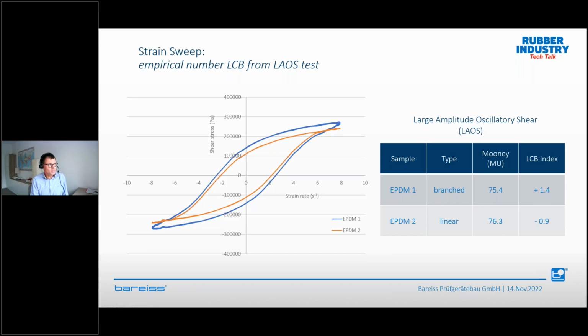Yeah. So just to summarize, we have two polymers which have nearly the same Mooney viscosity, but they are different in molecular weight distribution and long chain branching. So you cannot replace one by the other. Yeah, but the Mooney is the same. So please be careful, and please go ahead and run this test. And honestly, this will take around 10 to 15 minutes, and then you have real information about your polymer. Yeah, that's very, very important.